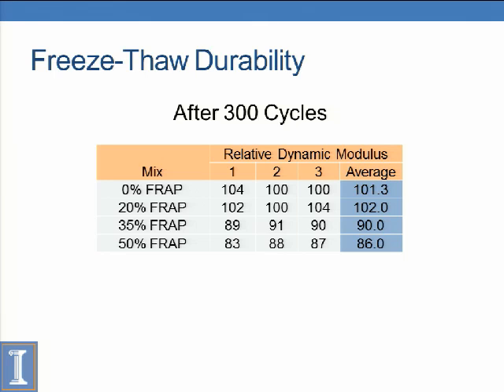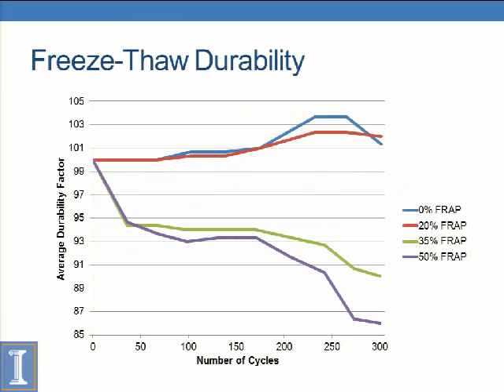Usually if you look at patching mixes, they will specify a durability factor of, say, 80%. This test actually ends at 86%. So in reality, we have pretty good freeze-thaw durability, and that's mainly due to the air entrainment we use. We have enough entrained air voids that our freeze-thaw resistance was pretty good.